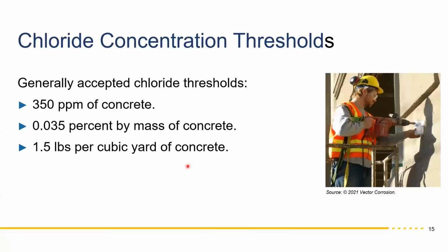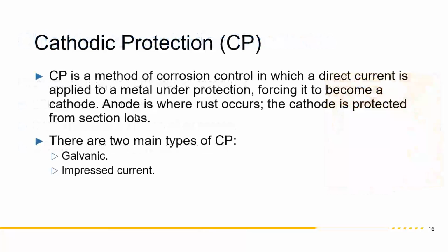So once you figure out where the corrosion areas are, you typically core and do a chloride profile, with lab testing at this point. You take a look at where the chloride profile is, and you do other tests like petrography, you look for ASR issues and so forth. And then once the core results, the lab results and field results are done, then you do modeling for the remaining service life. Once you figure out what the remaining service life is, how are we going to repair the bridge element?